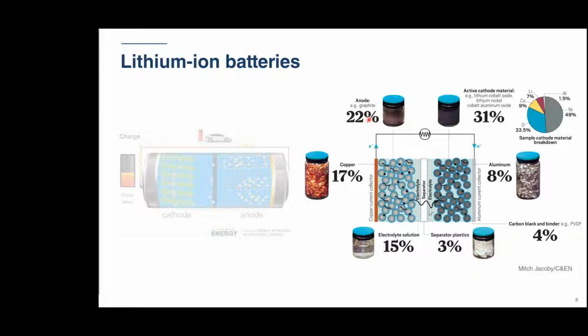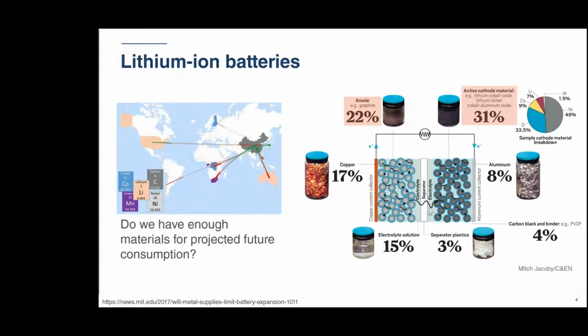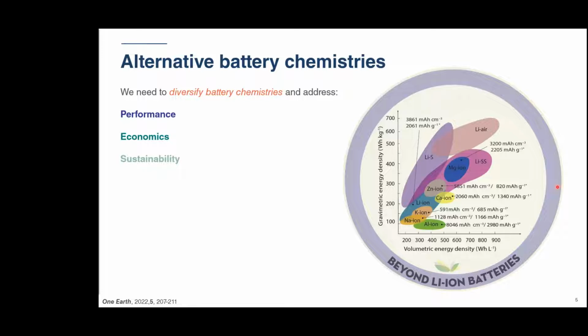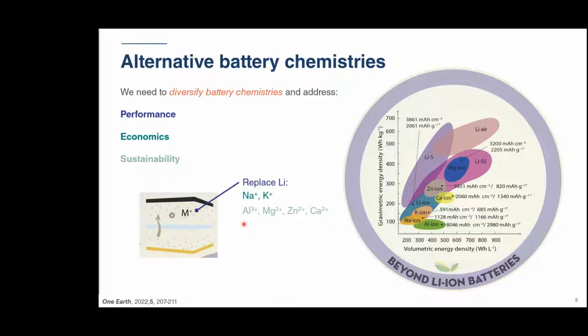The answer is that we need to diversify the range of battery chemistries that we use to address performance, economics, and sustainability. So here on the right, we have various different new battery chemistries that are being explored in their projected gravimetric and volumetric energy densities. And there are different ways of developing new technologies. So one way is that we replace the lithium ion for more abundant metals such as sodium or potassium, or multivalent ions like aluminium or magnesium, zinc, calcium. Or for applications where we do still require high energy densities, then we keep the lithium, but we can replace the cathode material for more abundant materials that have higher capacity, such as sulfur and oxygen.